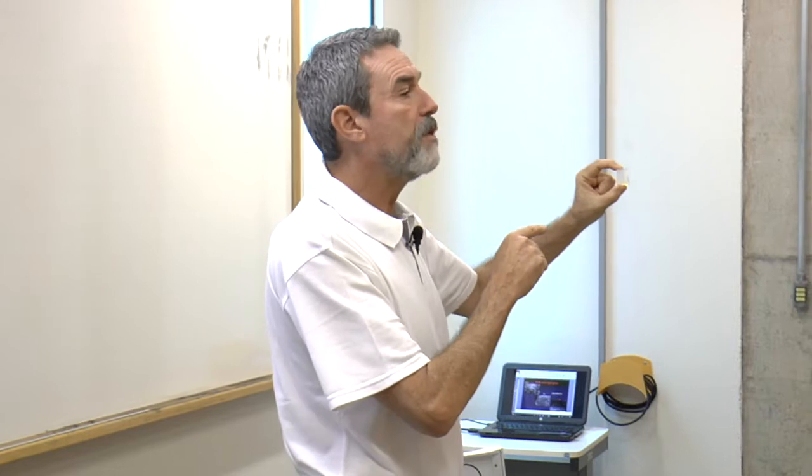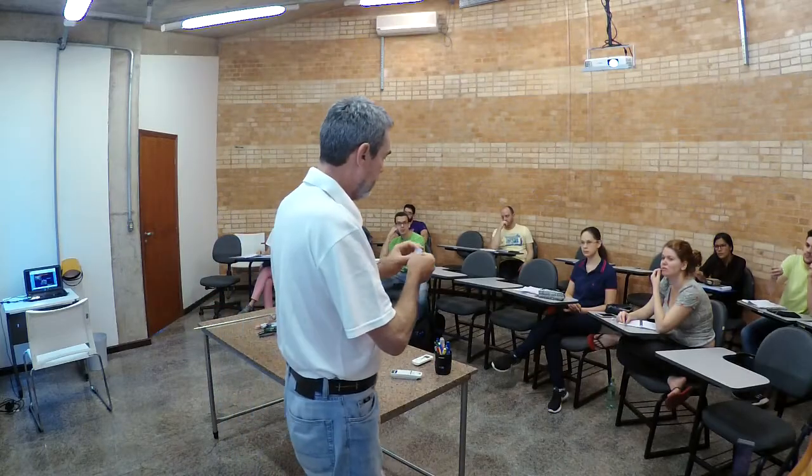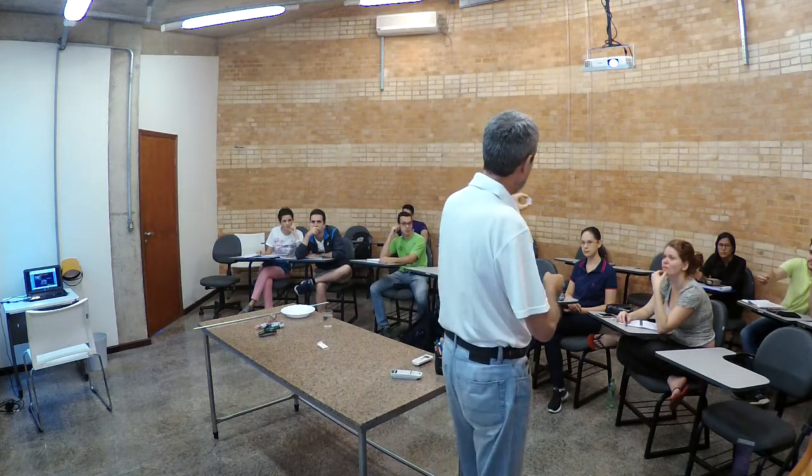There are no crystals inside. If you run an X-ray diffraction experiment with this piece of glass here, you see just an amorphous halo. No crystals inside. It's just particles, glass-in-glass phase separation.